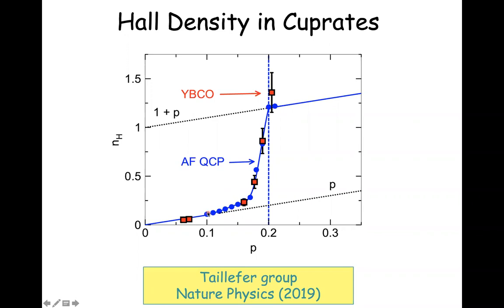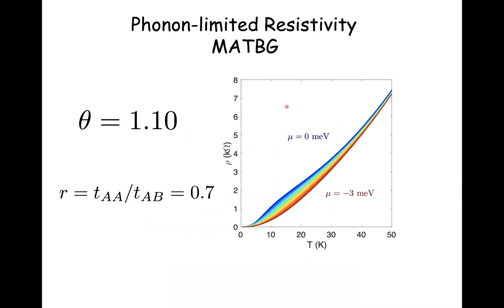So even though we can't do a neutron experiment, unfortunately, we don't expect that there's long range order of these spin and valley pseudospins in magic angle graphene. Instead, we have a pseudogap phase, and these jumps in Hall density are exactly the same jumps that are occurring in the cuprates, and where they occur is always very close to where there's superconductivity. And so should I stop now, Bob?